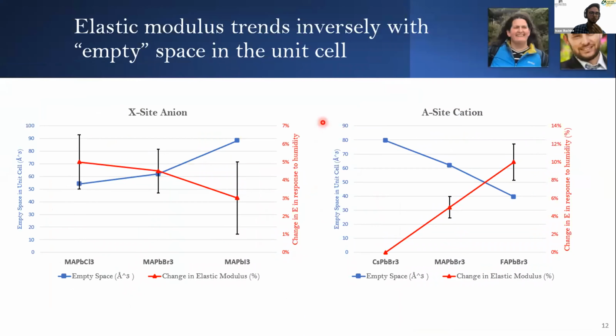But after a fruitful conversation with Anat Yitzhak of our lab and Professor Ilya Gruberg at Bar-Ilan University, what we found was the following: the elastic modulus, in both sets of crystals, trends inversely with the empty space of the unit cell. So in blue, as you can see for the X-site anion, when the empty space increases, the response in the elastic modulus to humidity decreases. And I would just like to take a moment to define what I mean by empty space.